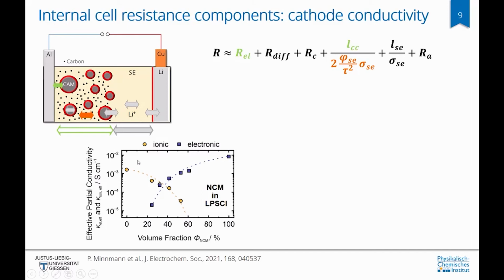the composite cathode. And we can see that there's an optimum value here around 40, maybe 50 volume percent of NCM, which incidentally is also the range where we obtain the best cell results in Gießen. Unsurprisingly, the ionic conductivity drops dramatically when the volume fraction of NCM is increased, and this is the biggest challenge for the composite cathode and having a low internal resistance.